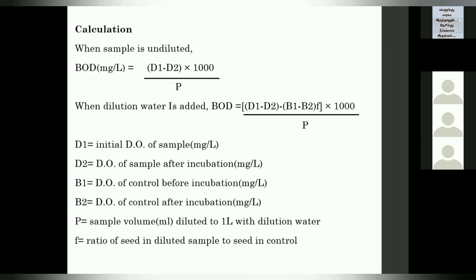Then this is the calculation for BOD, D1 minus D2 into 1000 by P when the sample is undiluted, and after dilution, D1 minus D2 minus B1 minus B2 into F into 1000 by P, where D1 is initial DO, D2 is the DO value after incubation, B1 is the control before incubation, B2 after incubation, P is the sample volume diluted to 1 liter with dilution water, and F is the ratio of seed in diluted sample to seed in control.